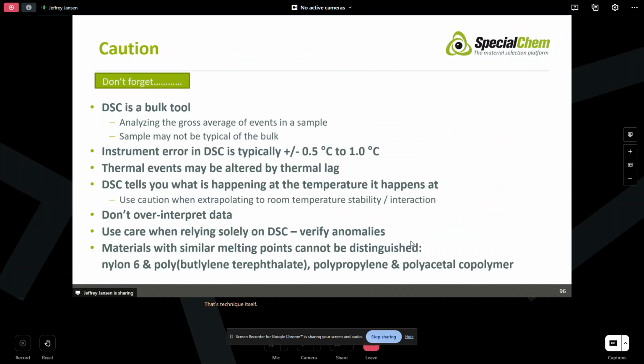And don't forget, DSC is a bulk technique. Again, it doesn't sound like it. You use 4 milligrams, but you're not necessarily analyzing some micro material. And by the same token, if you analyze a pellet or a section of a part, understand that if things aren't uniform, you're not necessarily going to get representative results. So sometimes sampling at multiple locations on a part or running multiple pellets is the way to go. Again, you just need to understand that.